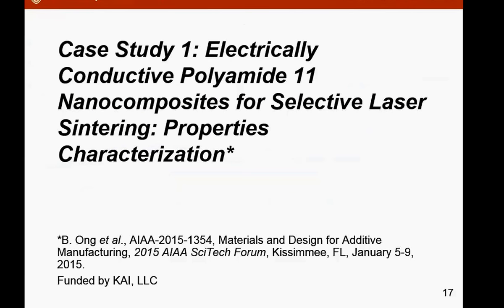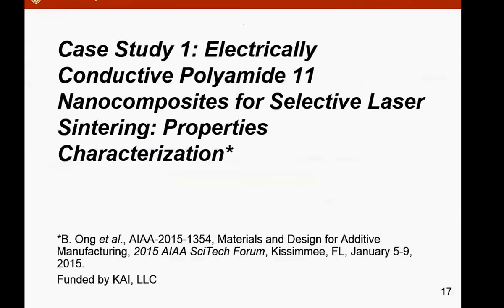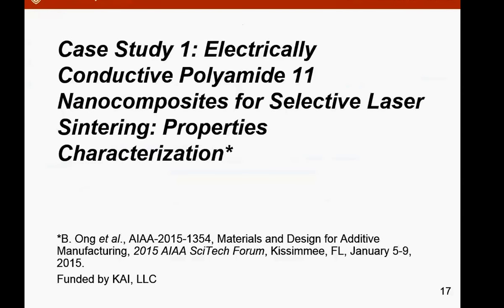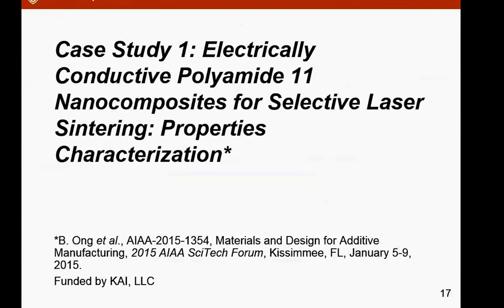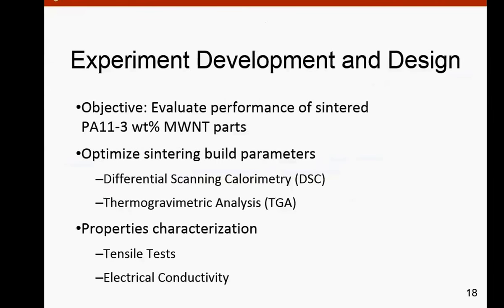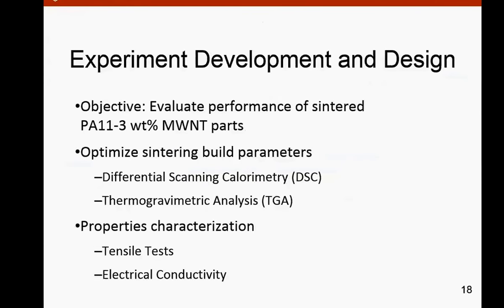Okay, so I'm going to give you some examples. All of these have actually been published by my students. Okay, and this one was published in 2015, and these have been presented at AIAA, and this is what we first did: electrically conductive nylon 11 for selective laser sintering. That's what we started. Okay, so I'm actually showing you the methodology of how we solve a problem. So we go through, we select actually 3 weight percent multi-wall carbon nanotube. But before we did that, we tried different weight loading. That's kind of our expertise, nano-composites. This is a nano-composite. We were able to use DSC, TGA, and eventually do all these characterizations.